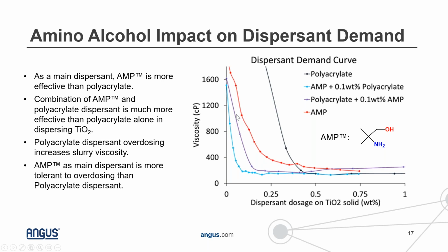You can also consider the case where you combine both the polymeric dispersant and a product like AMP. That's the curve in purple here, where we started with an addition of 0.1 weight percent of AMP, and then we started to titrate in the polyacrylate dispersant. And so we're already starting to get a pretty low viscosity of this grind. What we do notice is that if you keep adding the polyacrylate dispersant, your viscosity does start to creep up a little bit more, indicating that you might not have the best quality grind at those levels.